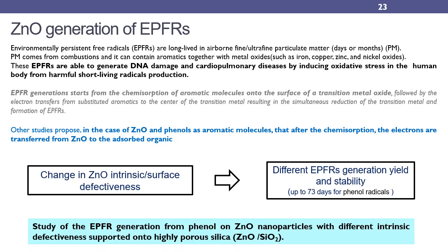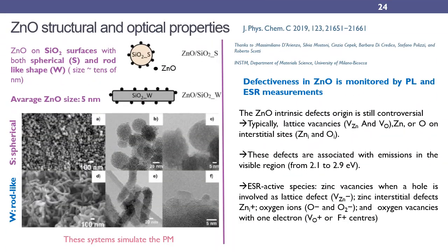Here, we consider zinc oxide nanoparticles on silica supports with different shapes. The investigation of the defectiveness of zinc oxide nanoparticles arising from the different structural, morphological, and surface features must be considered in relation to their surface reactivity in the formation of persistent radicals. Zinc oxide nanoparticles with an average size of 5 nanometers are anchored on silica supports with both spherical and rod-like shape. These systems simulate the particulate matter.